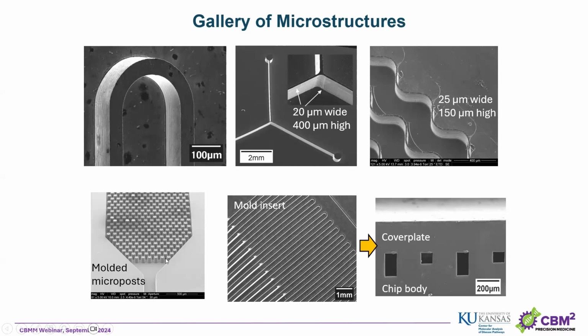The other example here is molded. These are micro posts molded from the machined brass insert. We can make designs that have different heights on the same mold. For example, if you try to do it with lithography, you would have to do two-step lithography, versus in micromilling, it's all done in a single step. And if you emboss these channels into the plastic, put the cover plate on it and cut it through, you can see how channels can have different geometry, I mean, different height, from the same mold.